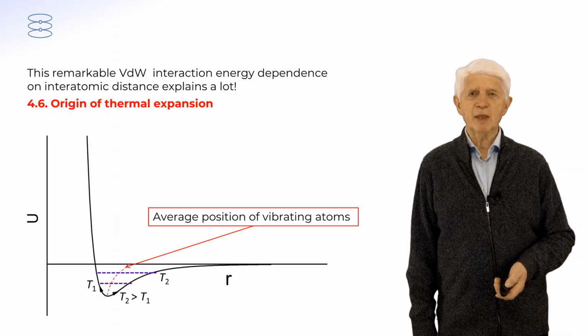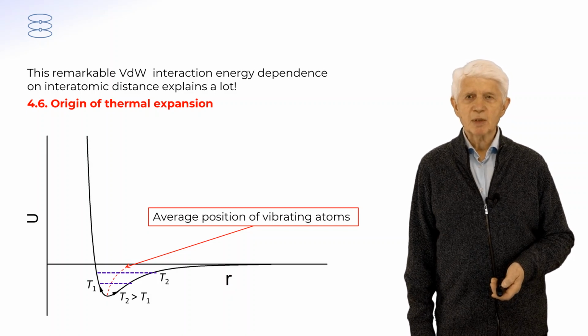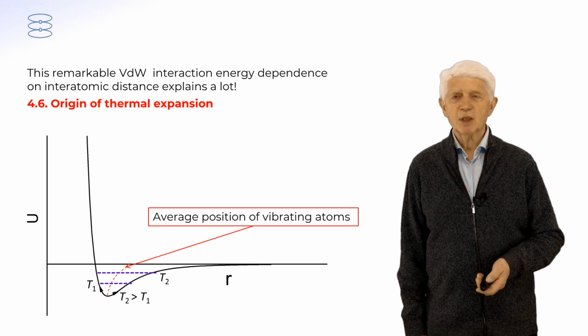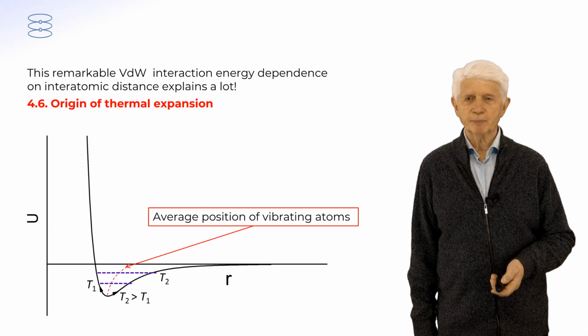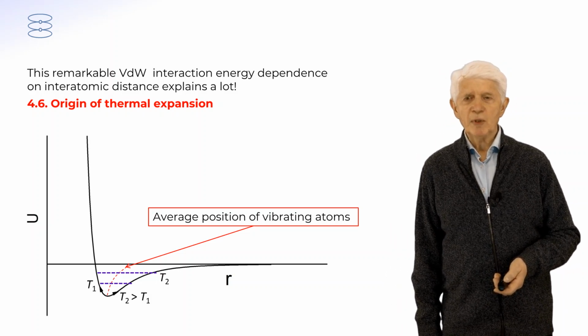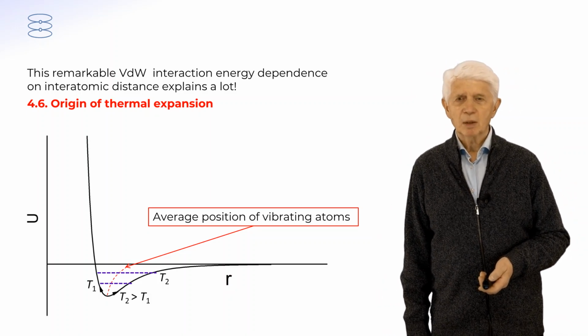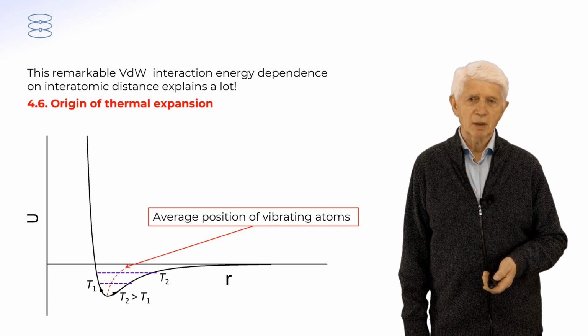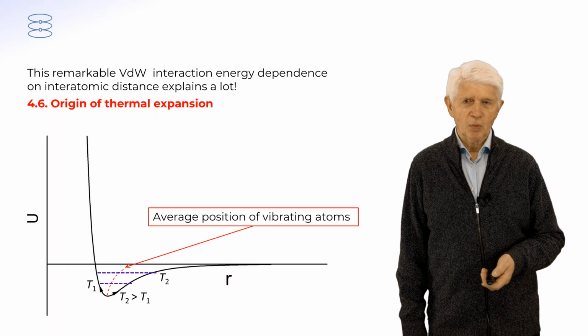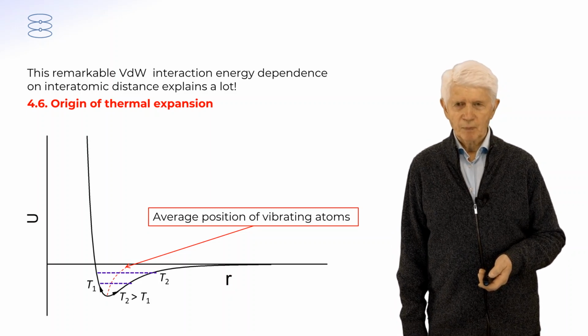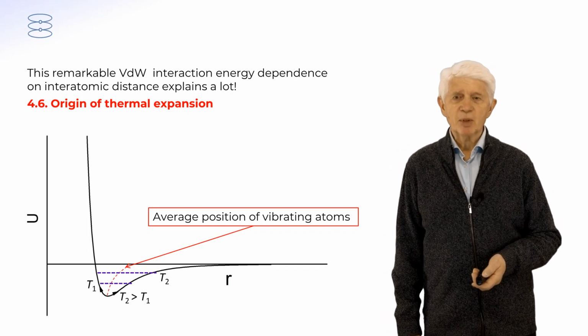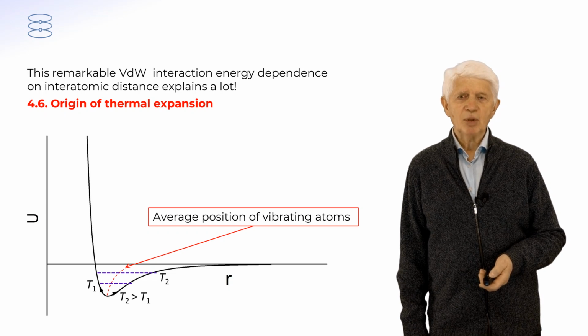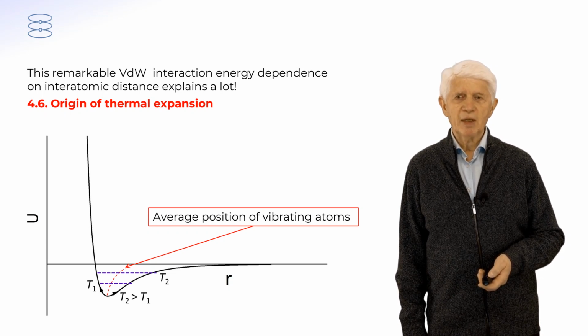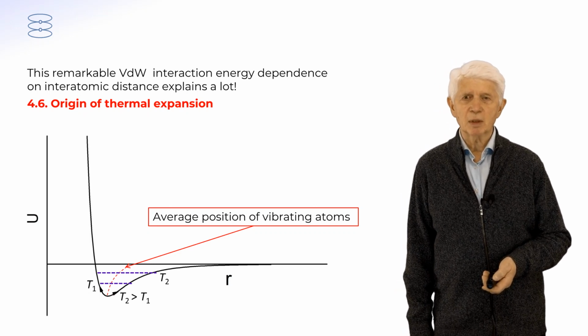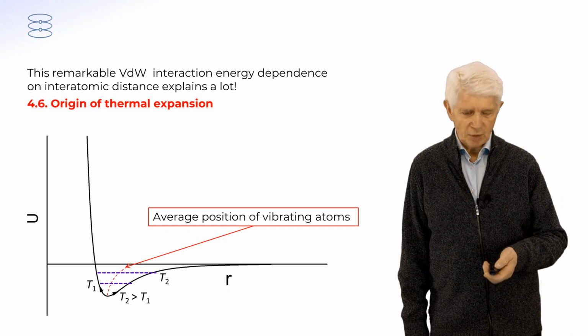This remarkable dependence of the van der Waals interaction energy on the interatomic distance explains a lot. For example, it immediately explains the origin of thermal expansion. Indeed, were the two wings of the potential symmetric, there would be no thermal expansion. But in fact, the right-hand side, the long range wing, is produced by a weak dipole-dipole fluctuating potential. And the repulsive part is much steeper. Therefore, as you increase energy, the amplitude of atomic vibrations increases, and the mean location of atoms necessarily should increase. This explains the thermal expansion of solids and liquids.